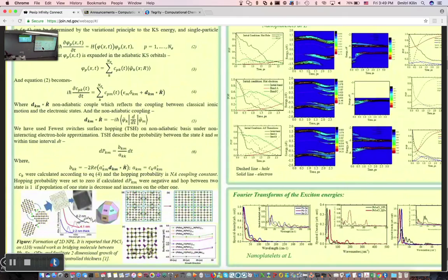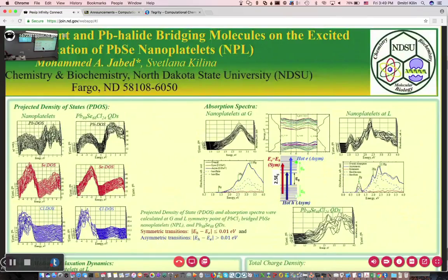The quantum dot is more flexible again, creating more thermal motion, mainly from the surface. The core is probably restricted in the same way as your periodic boundary conditions applied to your lattice along two dimensions for the nanoplates. So that's why you have more disorder there compared to the nanoplates. And again, overall, it looks like you have these discrete peaks in the spectra pretty much not very different from the L point spectra, right?